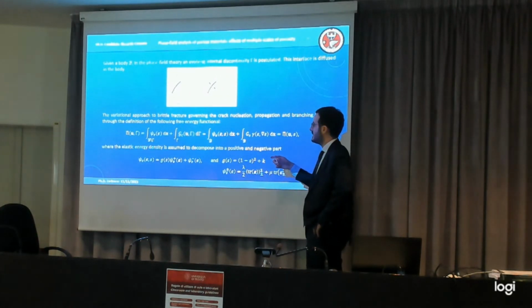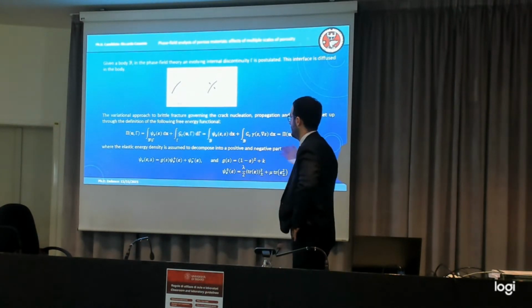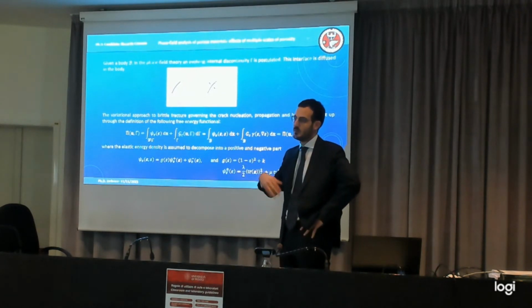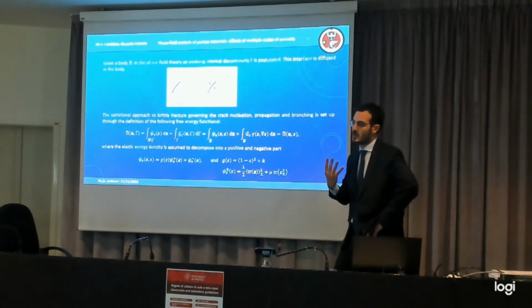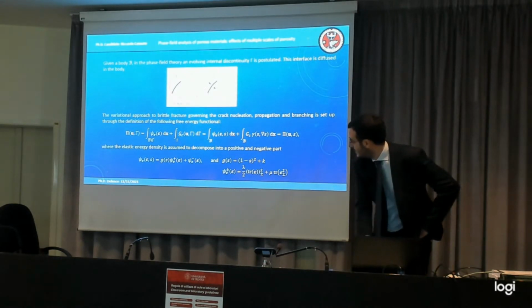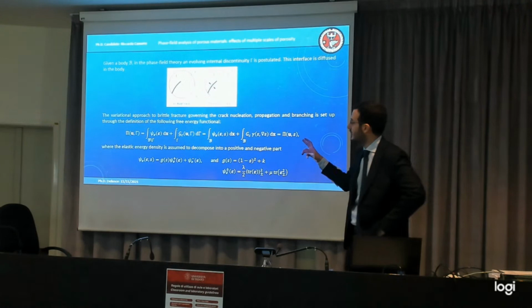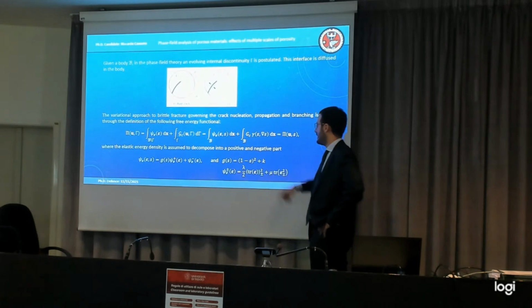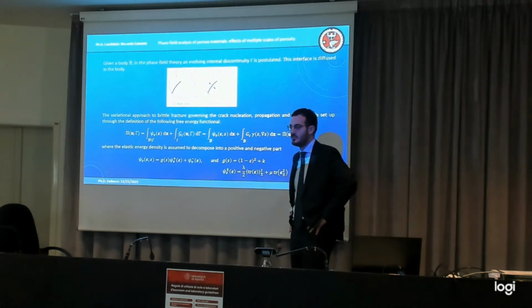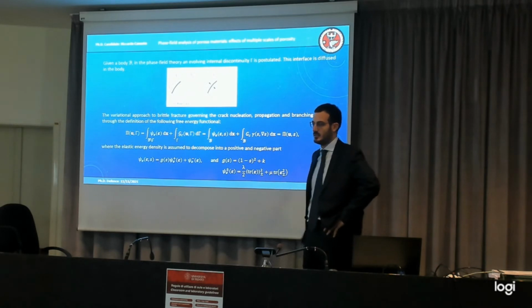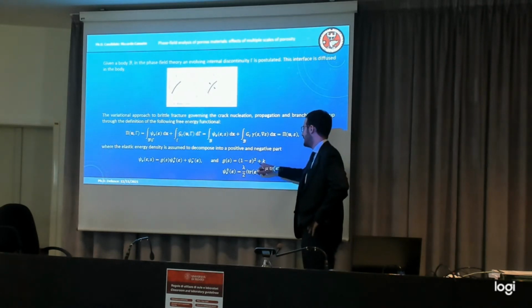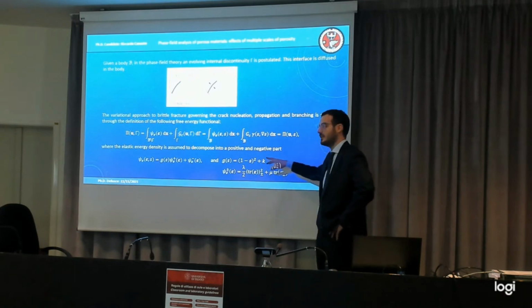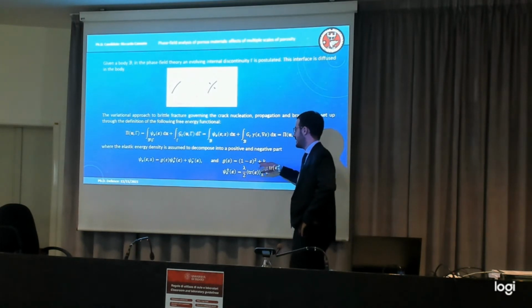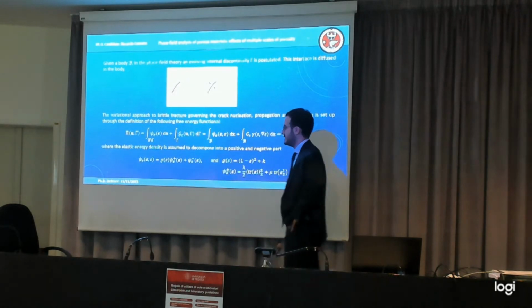And then the model is elastic, so this is isotropic elasticity. So you need the two elastic parameters. And so I would say 4 at this level: 2 from the linear elastic and 2 from the fracture. That is the k in g(s), right? This one is just to avoid zero stiffness and rounding errors in the simulation. So actually in the analytical treatment we have avoided reporting it, but it is explicitly inserted into the damage function. So you have these 4 parameters.